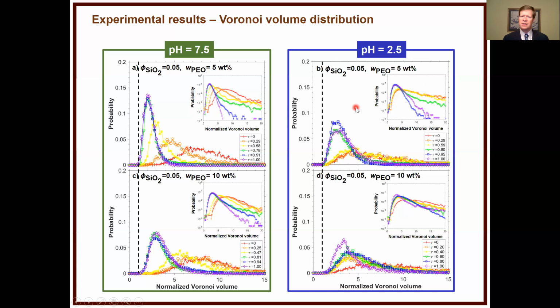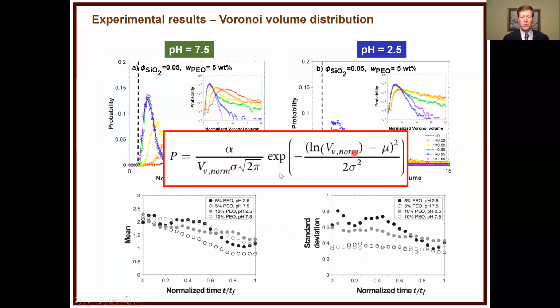And when we do that, we find something very interesting. So we can fit it to this log normal function. It looks a lot like a Gaussian distribution, with a log normal distribution of the Voronoi polyhedra. So mu is the mean, and this is the standard deviation of that fit. And so we use a 2-parameter fit.